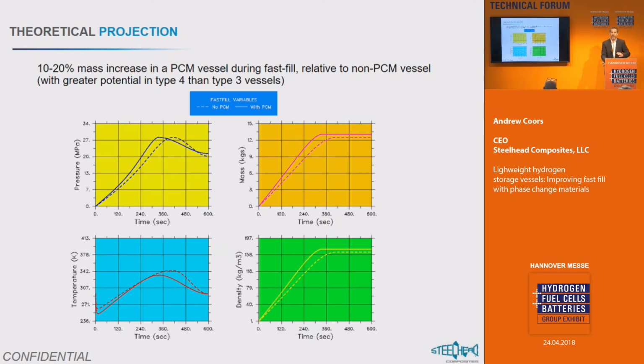So this is what happens during the fast fill process. Theoretically, if we were to include phase change materials in it, we needed to come up with a way of having a phase change material that changes phase at the temperature at which the gas is filling in a fast fill environment. The fast fill we're defining is something in 5 minutes to fill up the volume of the tank.